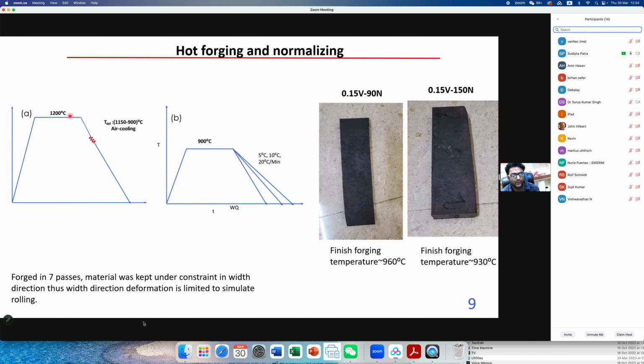We actually hot forged this steel because in our institute, hot rolling temperature will decrease very fast. Here with the laboratory steel, we try to simulate the hot rolling by hot forging, and we then normalize the steel at 900 degrees centigrade and cool at different rates: 5 degrees centigrade, 10 degrees centigrade, and 20 degrees centigrade.